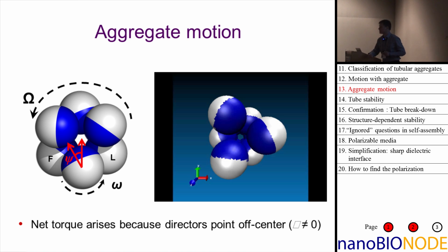because there's something very interesting going on here that goes to the heart of what holds this whole thing together, what makes it rotate, and what ultimately explains the stability of these tubes, and that brings us then to the topic of synchronization. If you look closely, you see that these particles have their blue, that is the magnetic side, not facing exactly toward the center of the tube, which would have been the state of the lowest energy, but they're lagging slightly behind, indicated by this angle psi. It turns out that that is a necessity. The particles find this lag psi by themselves.